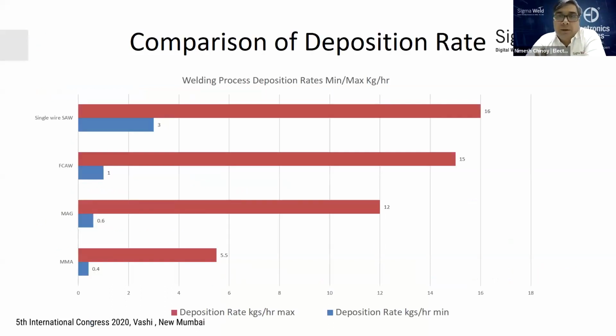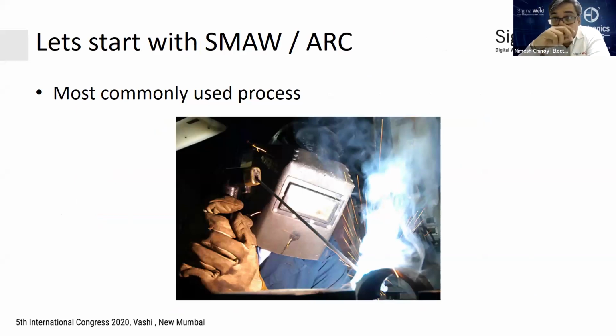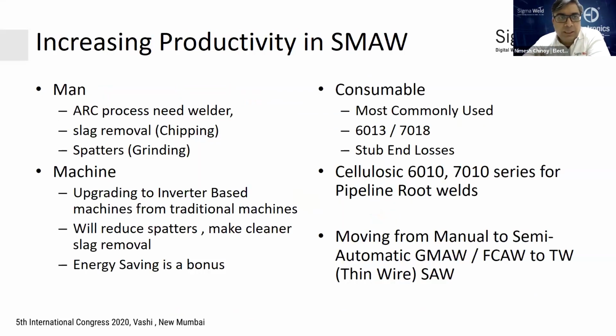If we quickly look at the comparison of deposition rates for different processes, you can see the highest among the standard processes is single wire submerged arc, ranging from 3 kgs per hour to about 16 kgs per hour. Flux core wire welding is 1 kg per hour to 15 kgs per hour. MIG-MAG goes from 600 grams per hour to about 12 kgs an hour. And arc welding, which is the most traditionally used, starts from 0.4 or 400 grams to 5.5 kgs an hour. The most commonly used process is arc welding even today in India and mostly globally as well.